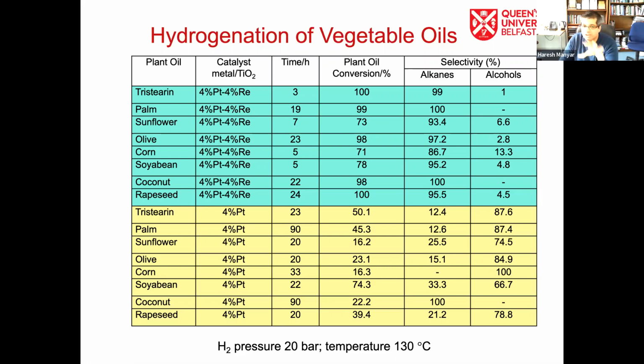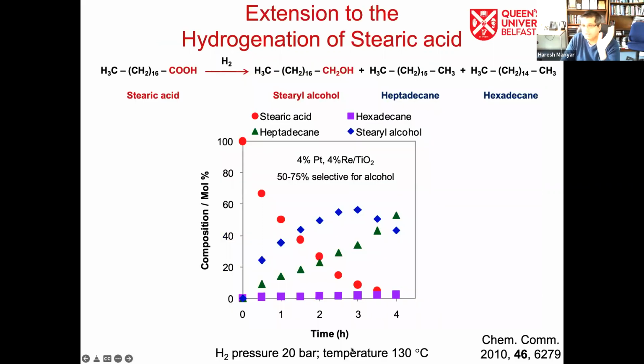steps, you know. The traditional chemistry would require taking the oils and then doing the reforming of that and steam reforming to break down the triglycerides into corresponding fatty acids. And these fatty acids then will be hydrogenated to alcohols. So it's a complicated process, requires a number of different unit operations. However, we can here directly in one step hydrogenate it down to alcohols or the alkanes as we require. And you can see the reaction conditions are pretty mild, 20 bar and 130 degrees temperature, which is much, much milder compared to what we saw in the traditional practices.